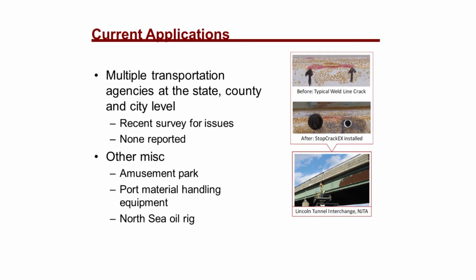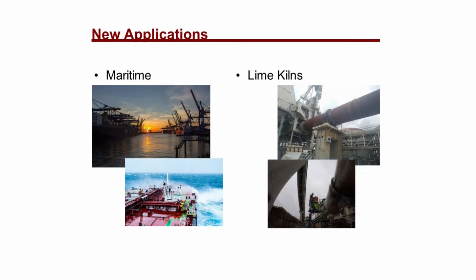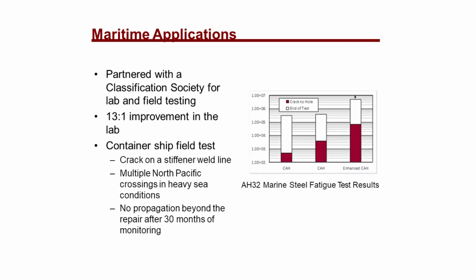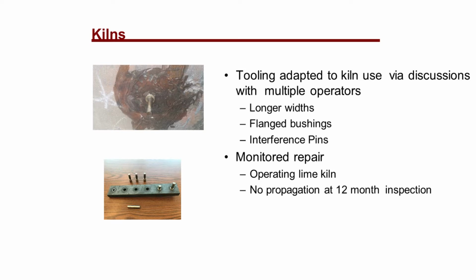Other miscellaneous uses: it's been used in an amusement park to protect structure there. I recently started putting it into port material handling equipment and a North Sea oil rig. We're going into some new applications that we've been developing for both maritime and lime kilns. The maritime is the same process that we use now for structural steel, but the lime kilns are a little more interesting. They require the hole to be filled because a lime kiln has material on the inside of it, and you don't want that to come out, even though we're not drilling through their insulation refractory. So we came up with a plug: we do the same process, but we drive an interference pin through to plug the hole.